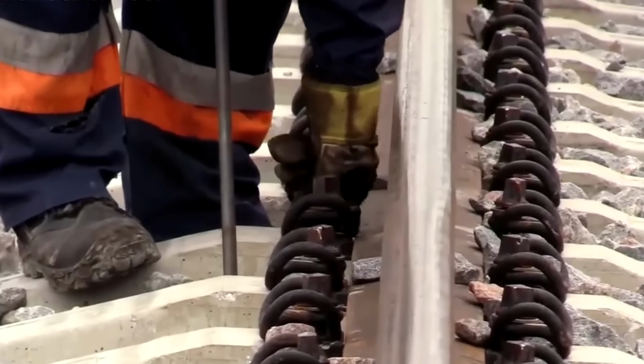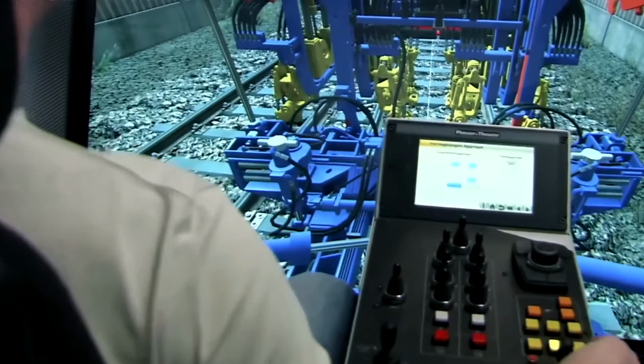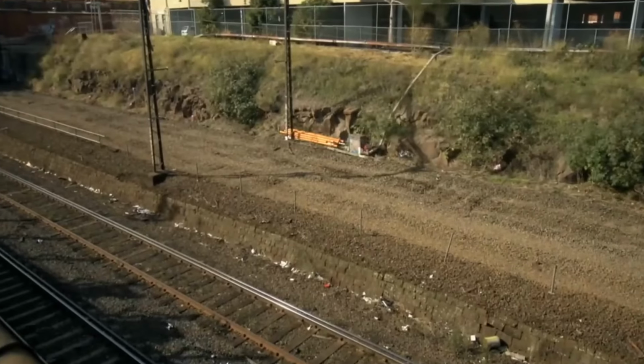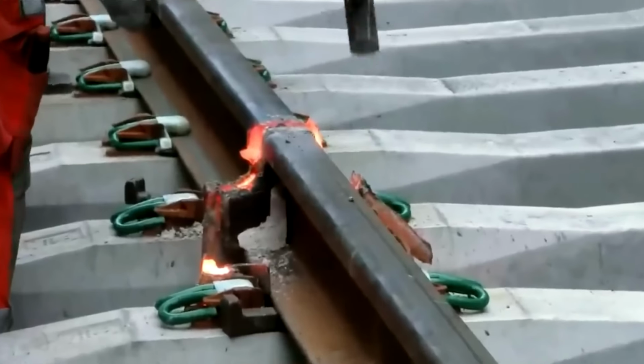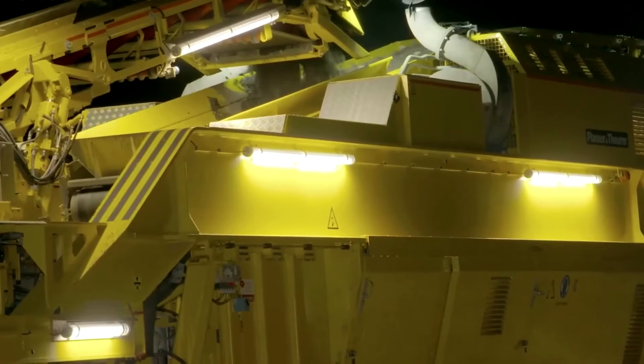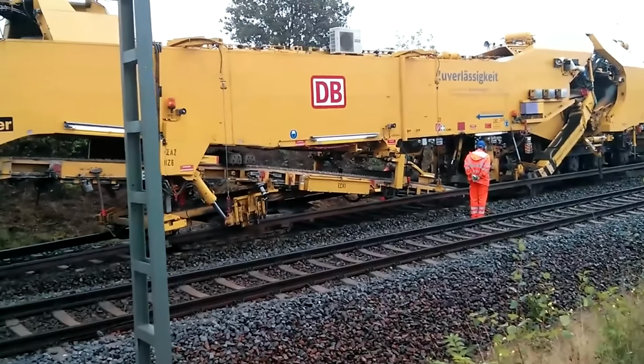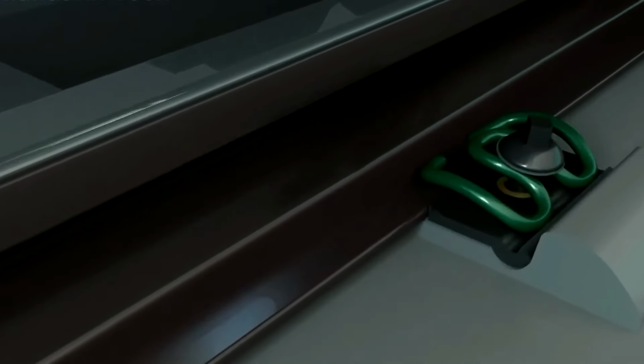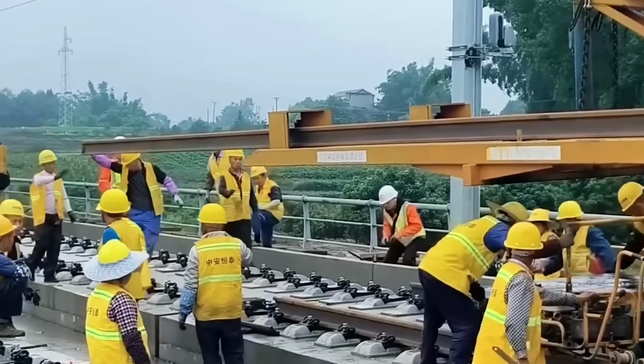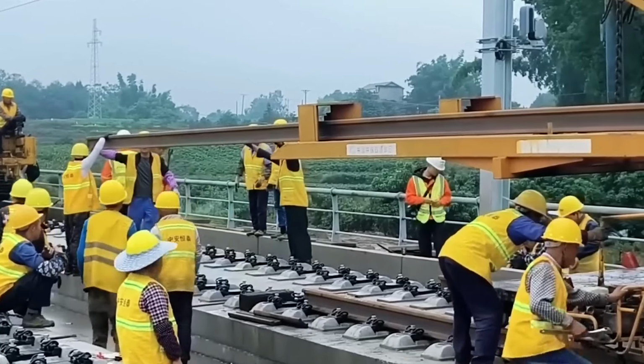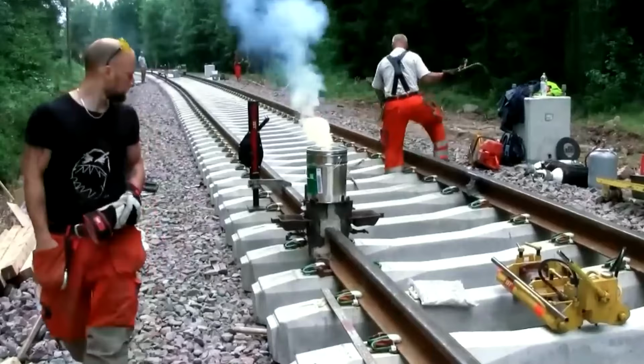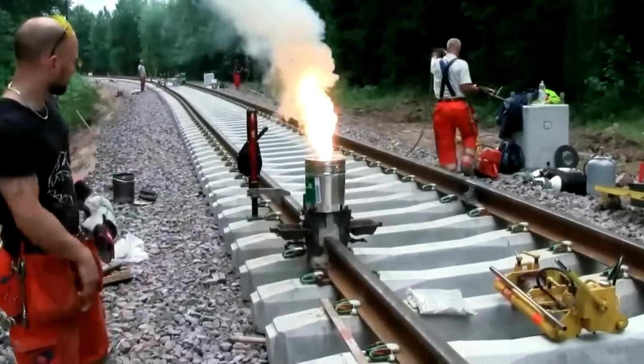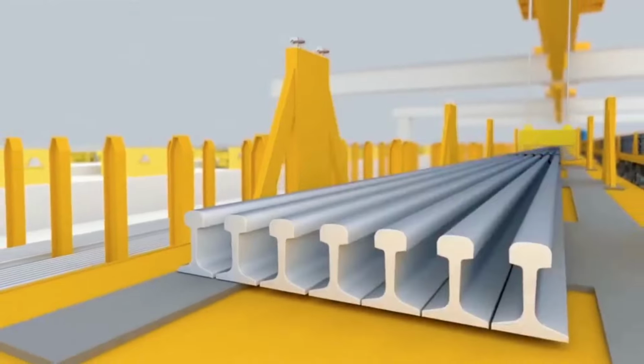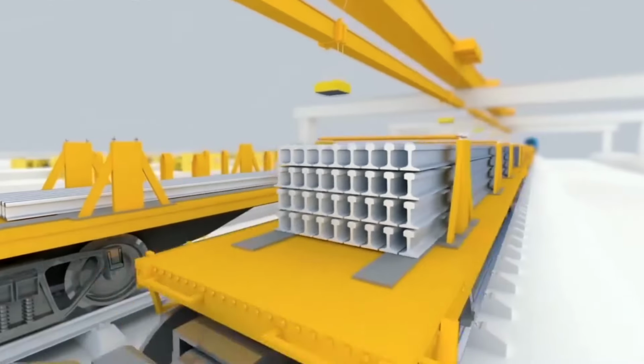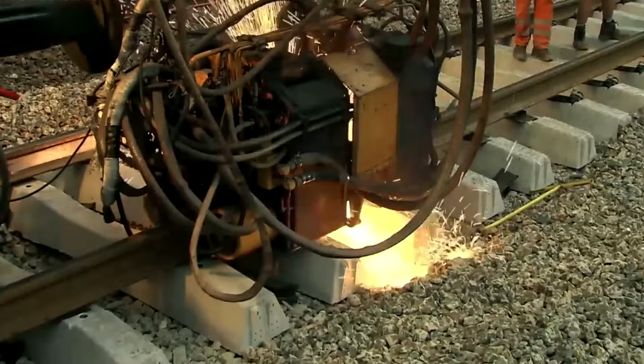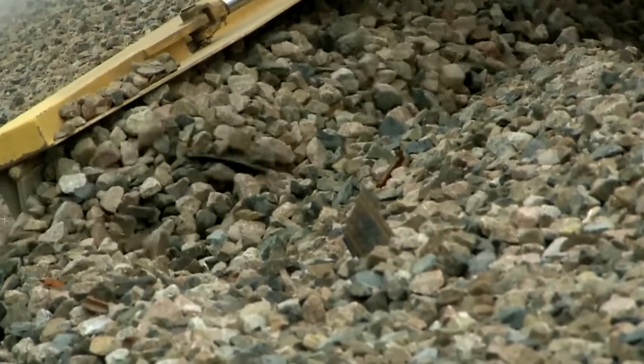Once the entire rail line has been welded and ground smooth, the final inspection begins. Engineers use an ultrasonic flaw detector to scan the rails, detecting microscopic cracks or internal voids hidden deep within the steel, flaws invisible to the naked eye. A track geometry car then measures elevation, tilt, curvature, and gauge width with precision down to 0.02 of an inch. Any deviation beyond tolerance is corrected immediately using tamping and alignment machines.